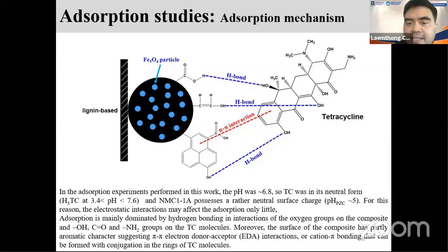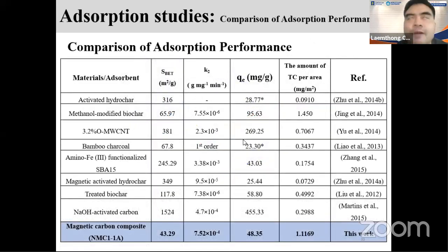Because the tetracycline has a lot of oxygen as well, which can interact quite well with the oxygen functionality of our adsorbent. And the tetracycline itself contains a lot of aromatic rings, which can interact quite well with the aromatic rings of our adsorbent by using the pi-pi interaction. So we did a comparison with what we can obtain from the literature. And we can see that the performance of removing the tetracycline in our system is not bad compared to the other works.